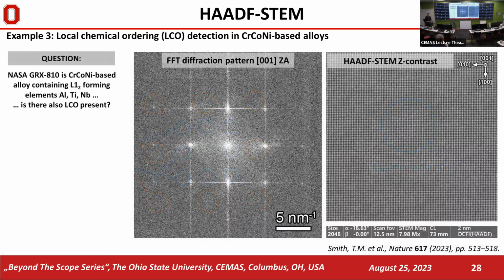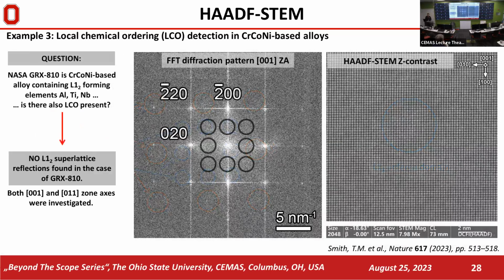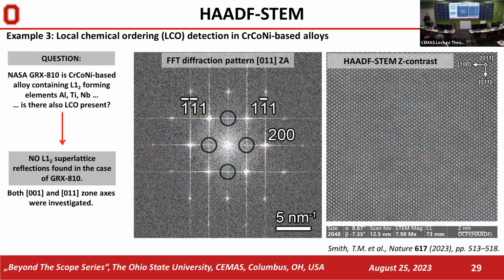For our GRX alloy, again, when I show the results, we don't see any superlattice diffraction. So when we compare to the alloy where we did the experiments, we are pretty sure that no ordering was present there.